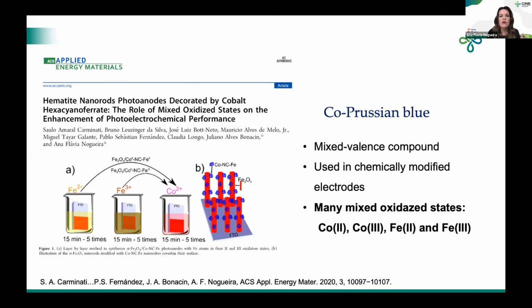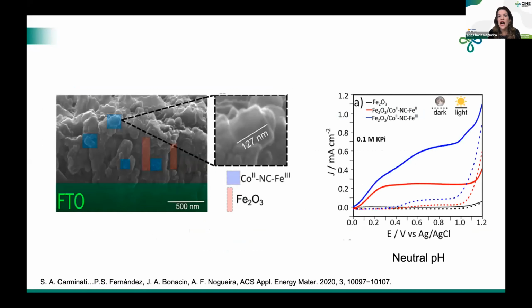So I'm going to show two examples. One of them was this work where we grew hematite nanorods, and we used cobalt Prussian blue as a co-catalyst. It was a collaboration between my group and the group of Professor Pablo and Professor Juliano. If you know about the cobalt Prussian blue, you know that there are many oxidation states. You can have cobalt 2 and 3, iron 2 and 3. So it's really complex. What we observed was a real increase in the photocurrent when you have this co-catalyst. This was done in neutral pH, which is an advantage. You can see here on this image the growth of this co-catalyst on the nanorods.